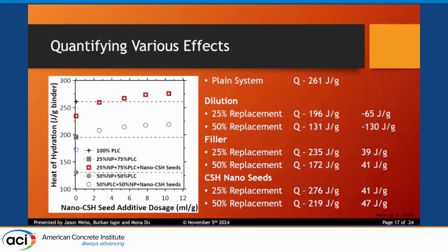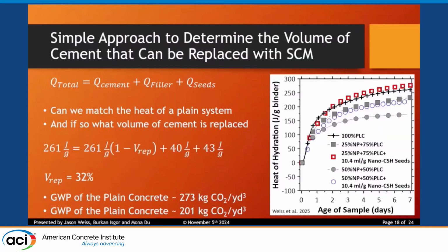When I first add the nano seeds in, I get some benefit, and then that benefit starts to go down as I go further and further along, right? So now I can actually start to design the system to behave very similarly. Here I've done it at 7 days, I could do it at 1 day, I could do it at 3 days, but I can say I need to get a certain total heat, which is a certain amount of reaction products. To do that, I'm going to take my cement plus my filler plus the heat that's associated with the seeds.